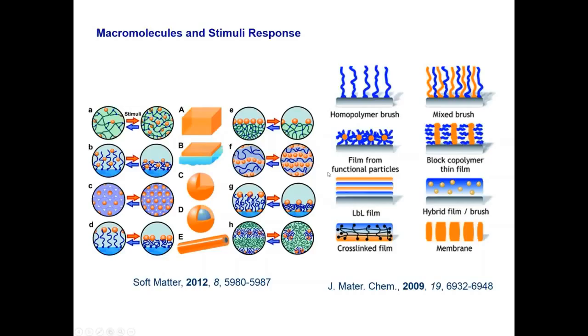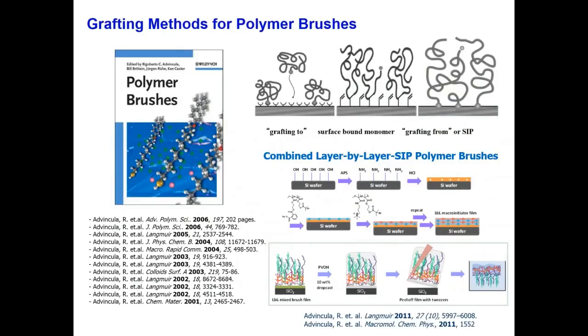This can lead to changes in film composition or even micellization or colloidal phenomena of polymer material components. Several years ago we pioneered techniques on grafted polymer systems, where we tether polymers to surfaces by grafting-to, grafting-through, or grafting-from methods. We can use the stimuli to change the response of the polymer towards wetting, swelling, patterning, or sensing. I will be showing several examples demonstrated on surfaces.